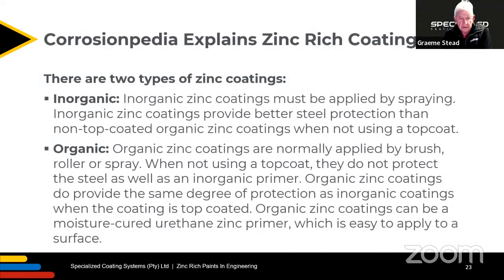There are two types of zinc coatings: inorganic and organic. Inorganic zinc coatings must be applied by spraying. Inorganic zinc coatings provide better steel protection than non-top coated organic zinc coatings when not using a top coat. Organic zinc coatings are normally applied by brush, roller or spray. When not using a top coat, they do not protect the steel as well as an inorganic primer. Organic zinc coatings do provide the same degree of protection as inorganic coatings when the coating is top coated. Organic zinc coatings can be a moisture-cured urethane zinc primer, which is easy to apply to a surface.